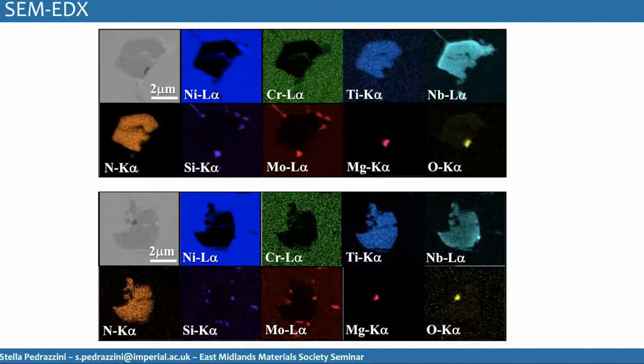So at this stage, what we have shown is actually that it wasn't a corrosion failure at all. There's a surface scale that is continuous and protective. One of the samples has a deposit of a fuel additive on top of it, but it hasn't broken through. So at that point, we started looking at these nitrides. And the nitrides now, they're titanium and niobium rich, and nitrogen. And then all around it at the grain boundary, there are these silicon-molybdenum rich phases.